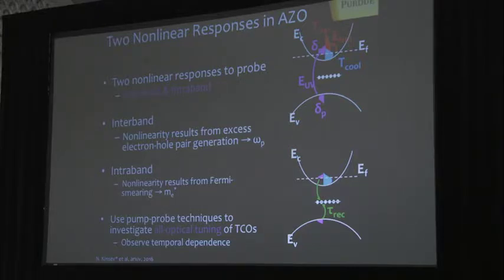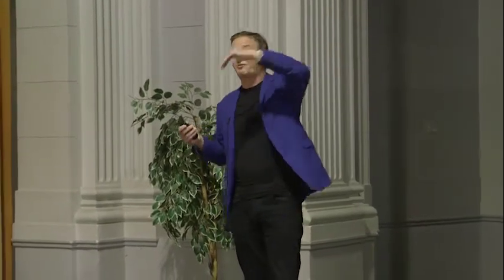This is for the case of interband excitation, but you could also do intraband excitation. So in this case, let's say we use a pump at 800 nanometers, so you stay in the conduction band. It turns out that because you increase the temperature of hot electrons, there is this Fermi smearing, and as a result an increase in the effective mass, which means that your plasma frequency would be redshifted.